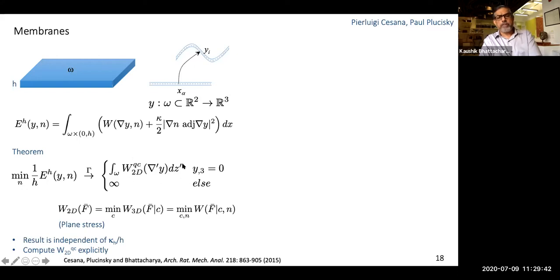And you can obtain the effective behavior from the 3D behavior by only looking at the first two columns and minimizing out the third column. In engineering, we call this plane stress. But that introduces some structural instabilities, like wrinkling, and then you relax against it and you get the effective behavior here. One of the things that is really remarkable is that this limit is independent of the ratio between these two small parameters.